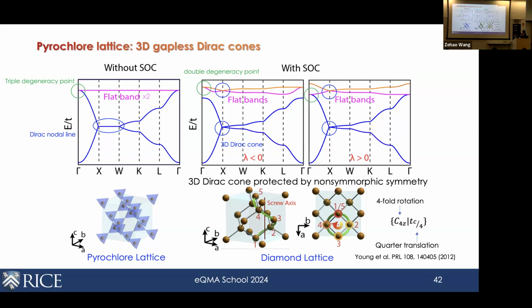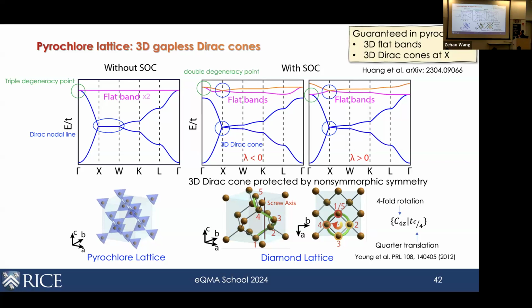There's a symmetry, a 4-fold in-plane rotation plus this quarter translation along this axis, and because of this non-symmorphic symmetry, any band crossing at the X point of the Brillouin zone remains a gapless 3-dimensional Dirac point. That translates to the pyrochlore lattice as well. So to summarize, there are 2 key things we look for in a pyrochlore. One is that the flat bands are flat in all 3 momentum directions, kx, ky, kz. The other is that you should have Dirac points at the X point of the Brillouin zone.